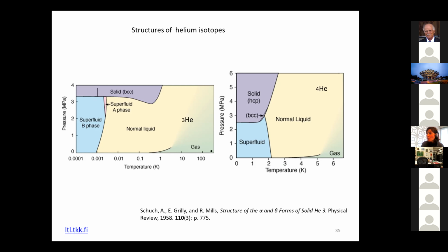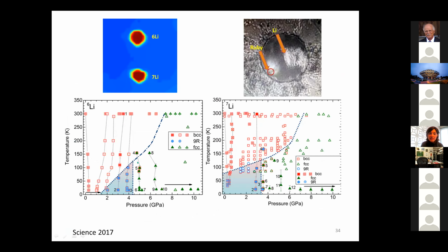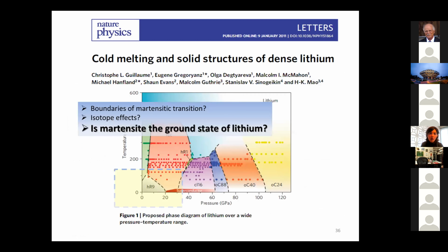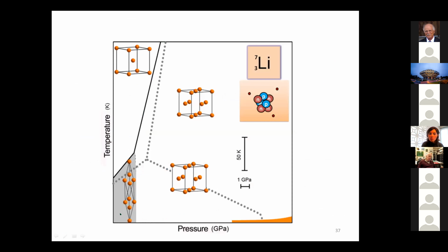We think that the differences in these boundaries of lithium 6 and 7 are related to the presence of some kind of dynamic effects coming from disorders that originate in the zero point motion. Now, one more question was, is this Martensitic phase the ground state of lithium? Well, we know that every time we cool down, the lithium lands in this 9R, and that was a great argument that this is the ground state.